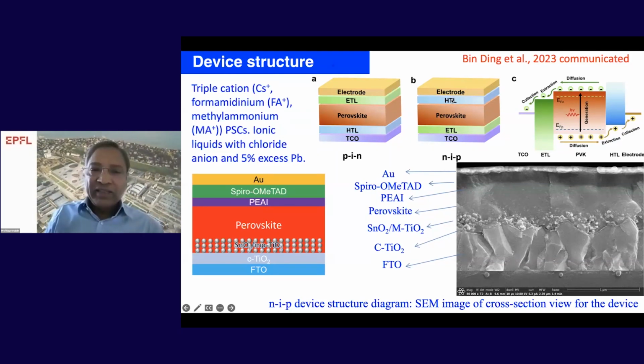Followed by that, you have an HTL in the NIP configuration. In the PIN configuration, you have an ETL layer. So these are the two dominant configurations available. Here I highlight that most of the studies in the literature use a triple cation perovskite: a small percentage of cesium, a majority of formamidinium, followed by a small amount of methyl ammonium. There is logic for using these three cations, in order to enhance the stability and the phase stability of the alpha phase of FAPbI3.